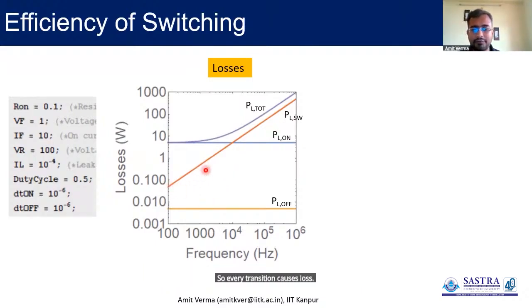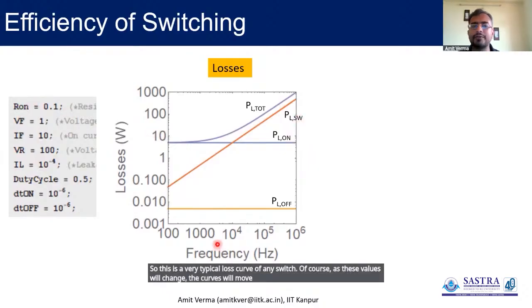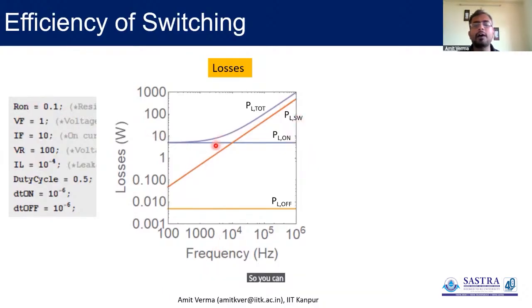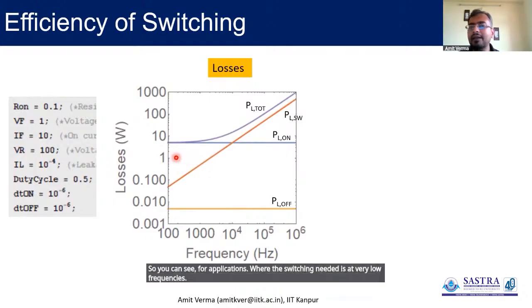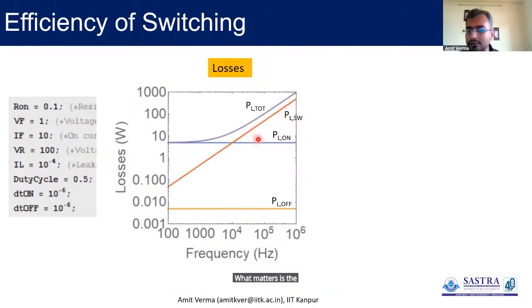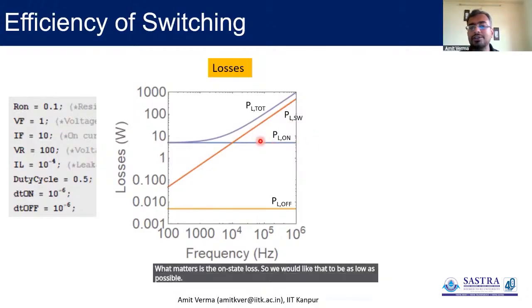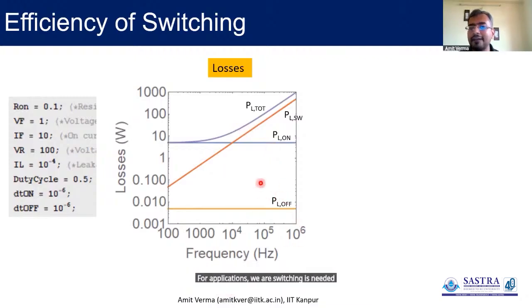So this scales with frequency. This is a very typical loss curve of any switch. Of course, as these values change, the curves will move around and the values will move around. So you can see for applications where the switching needed is at very low frequencies, what matters is the on-state loss. So we would like that to be as low as possible. For applications where switching is needed at relatively high frequency, the dynamic power loss actually dominates the total power loss.